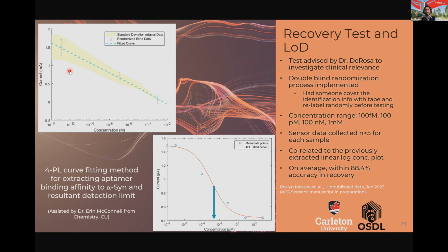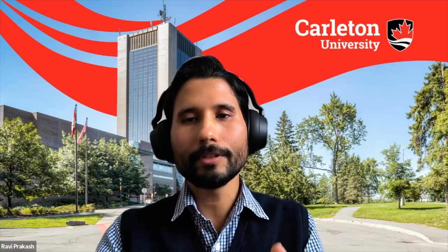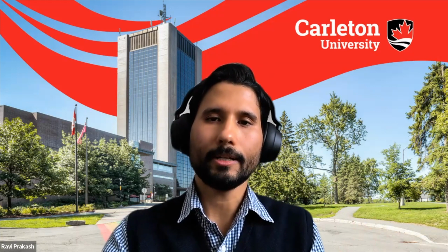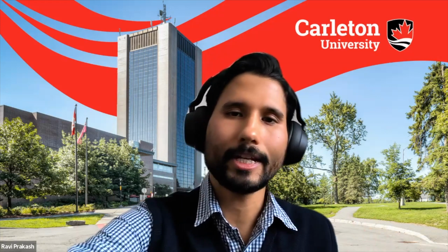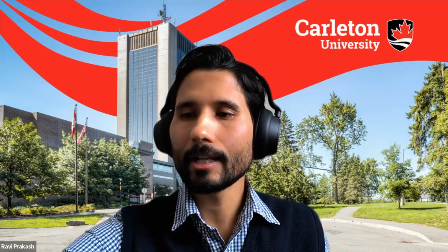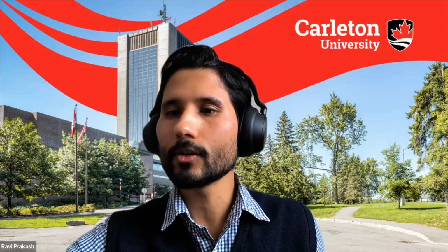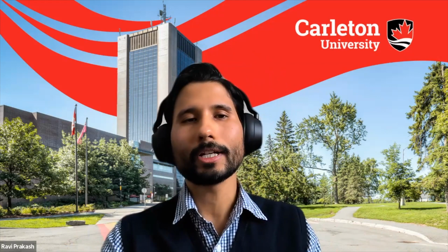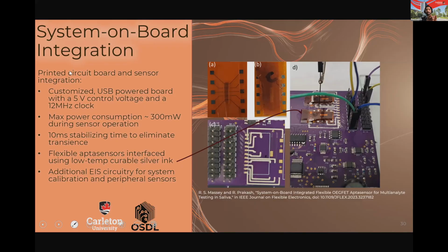We have also done another sanity check, so binding affinity quantification to show that the aptamer binding on surface binding affinity is comparable to aptamer binding affinity in solution, which we believe is the case. A lot of the testing we do using benchtop setups because that allows us to collect good data. But in parallel, we also constantly create integrated footprints so these aptasensors can be deployed in portable configurations.